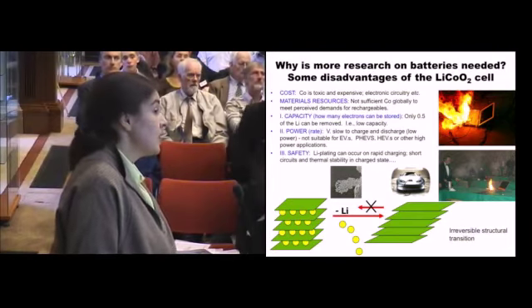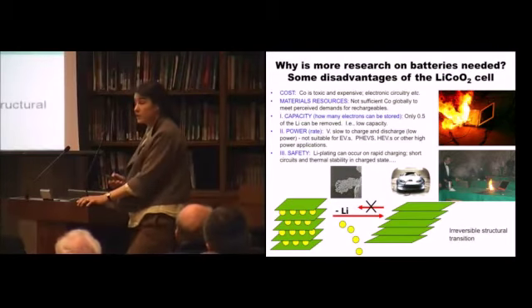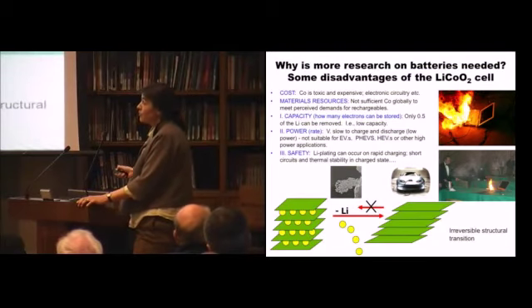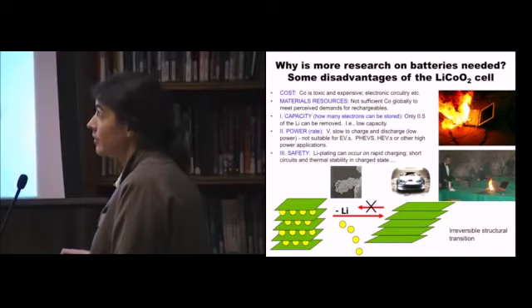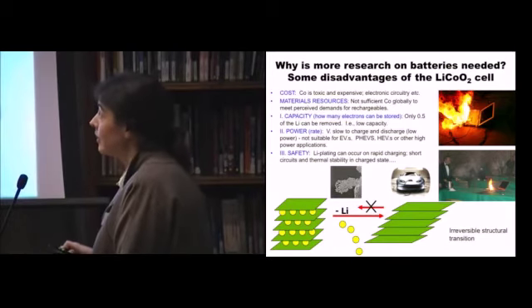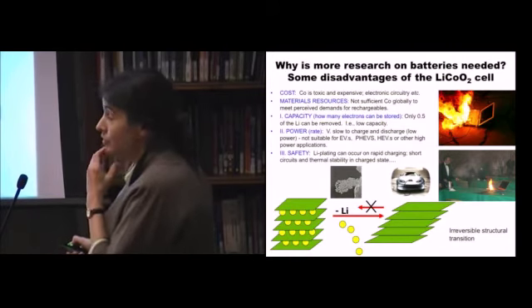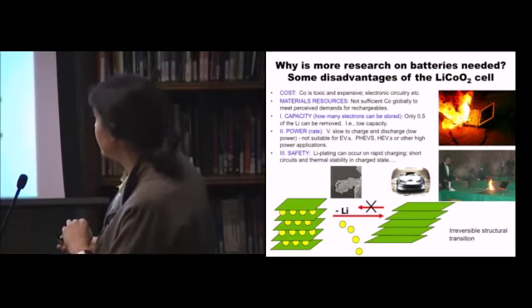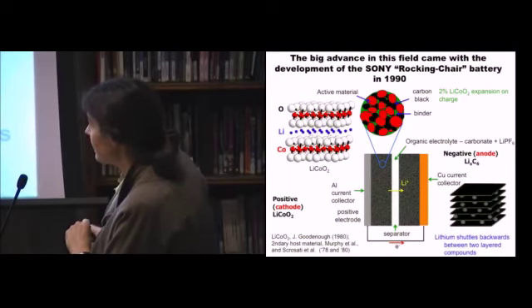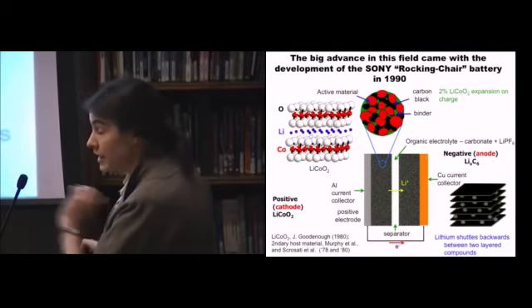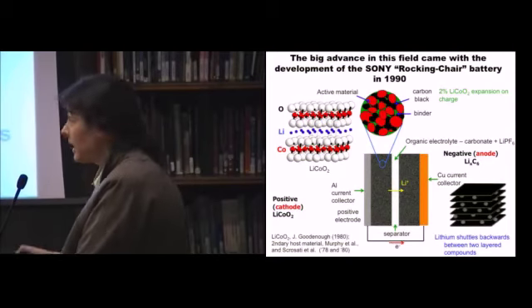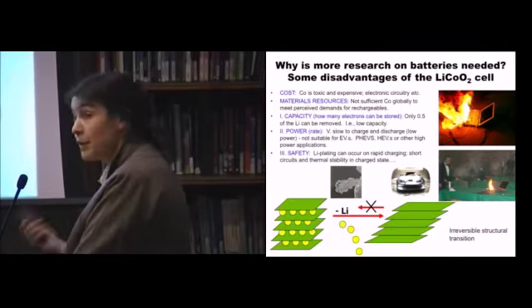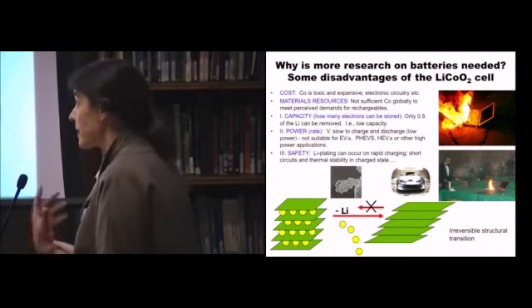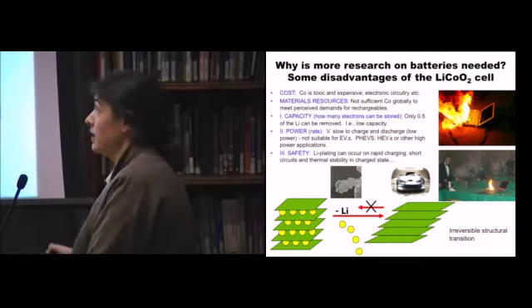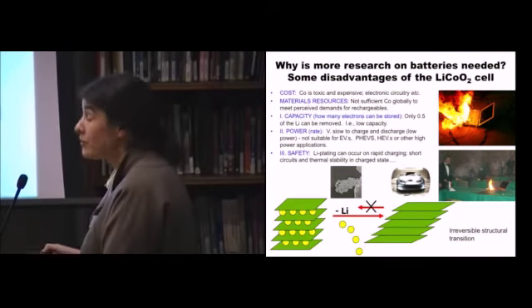Then you've got a power issue. So those of you who try to charge your laptops up as you're desperate to get on a plane or on a train will, of course, know that you just can't get the lithiums in and out fast enough, and it's just not fast enough for an electric vehicle. And then this issue of safety that I've been talking about. So if you charge your battery too fast, instead of intercalating the lithium safely in these graphitic sheets, what you actually do is end up growing dendrites on top of the carbon, and those dendrites can short-circuit your battery and cause safety issues. And so a lot of batteries that are taken apart will actually catch light because of the lithium plating that's going on, even in the batteries, I'm afraid, that you've got in your own laptops.